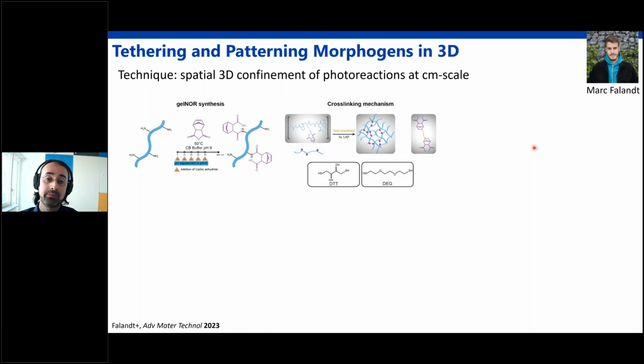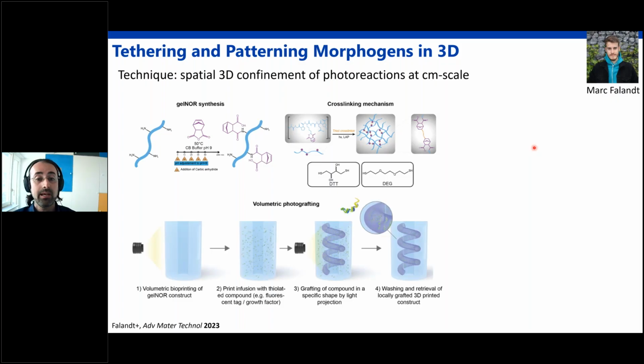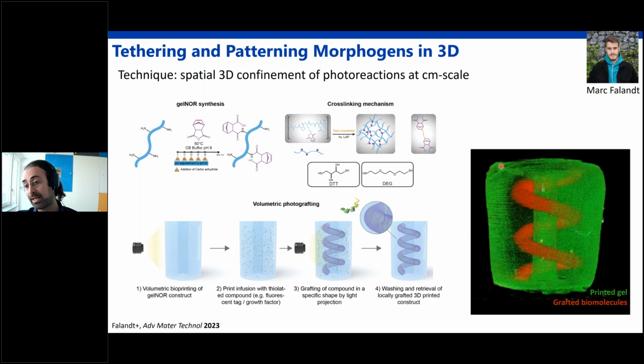We can also think of this process for first printing, but then also to add any thiolated compound, performing a secondary printing step, so that the compound will be grafted, or painted a bit, in the path that we want. If you see this example here, the green part, which is just a cylinder with a small channel in the middle, is what we first print with the printer. And the red part, this red spiral, is not physically an object, but is a trail of growth factors that is attached in this geometry.